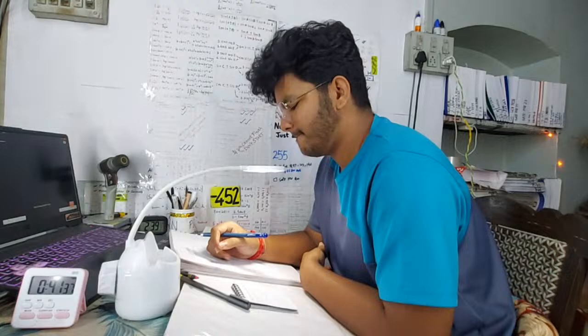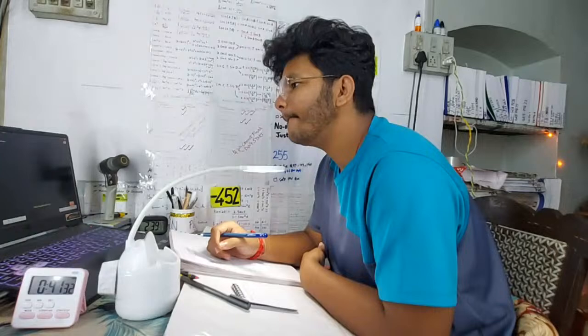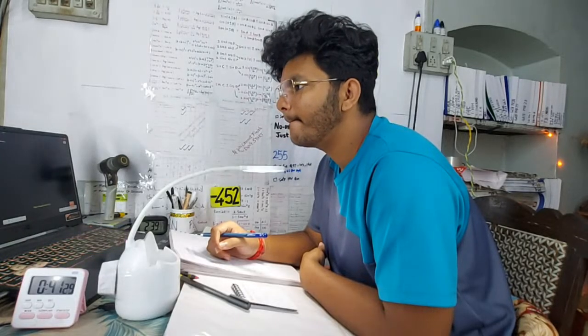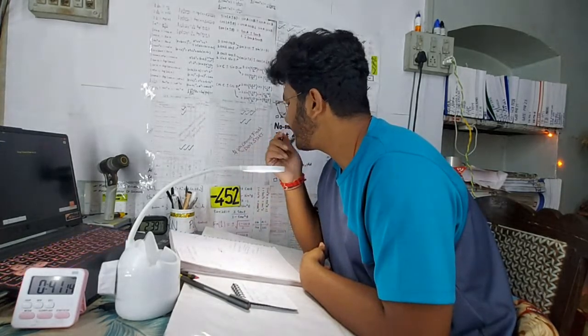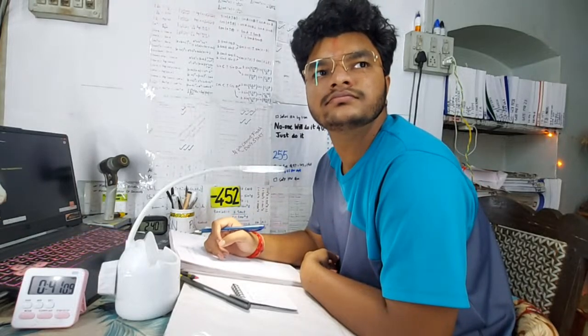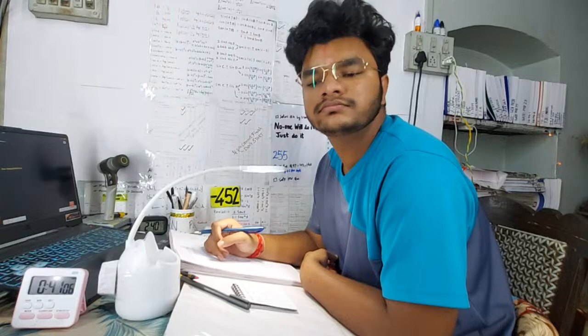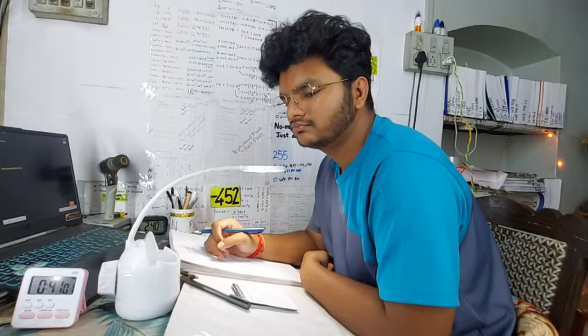Similarly, take another eutectoid steel sample, rapidly cooled to a temperature like, for example, 550 degrees centigrade. Then you start the holding time at time t equal to 0 at this constant temperature. After holding for a little while, the transformation begins. So we try to find out the beginning time of austenite transformation into pearlite at this particular temperature. We call it B3, the beginning time of austenite to pearlite transformation. Then we keep watching the microstructure until the transformation to pearlite is complete. The transformation completion time is called E3, the ending time of austenite to pearlite transformation. All right. After coming down to this particular temperature,